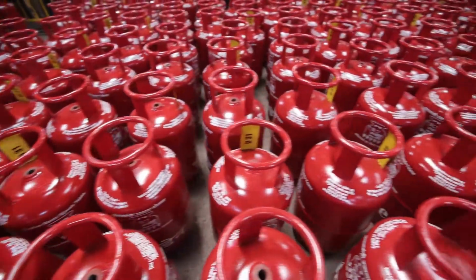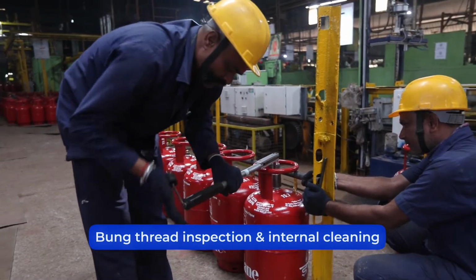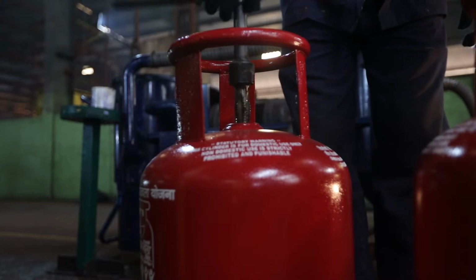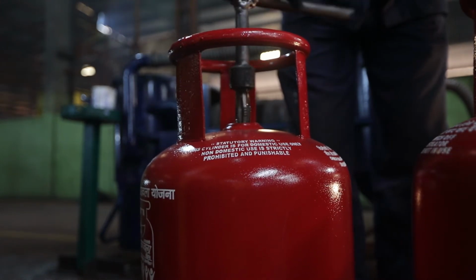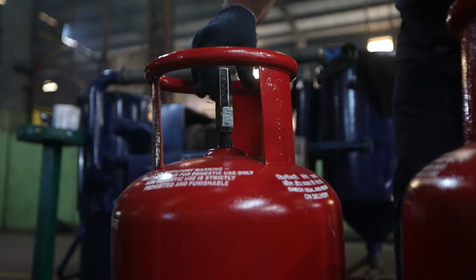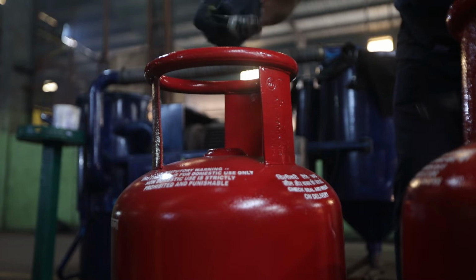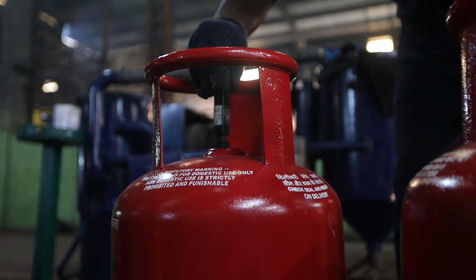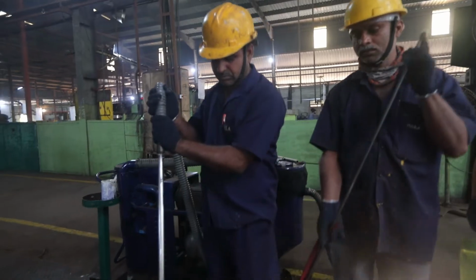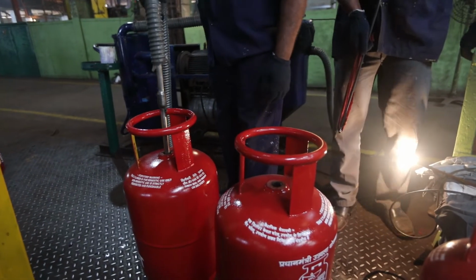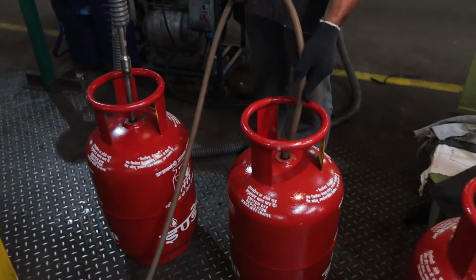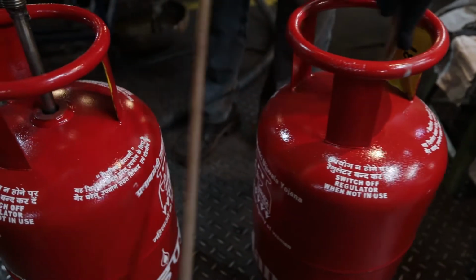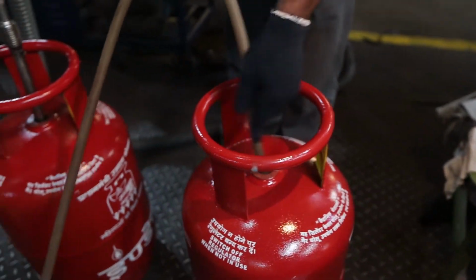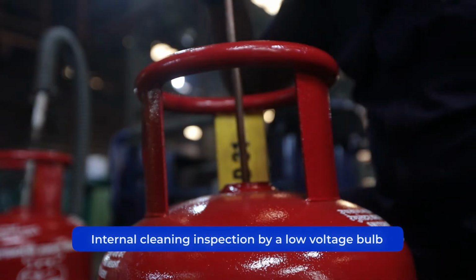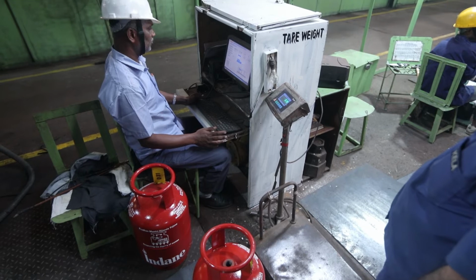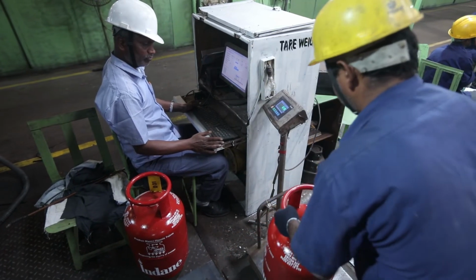An operation for bung thread inspection and internal cleaning includes: Step 1. Bung thread cleaning by a 3/4 inch NGT finishing tap and checking by L1 and L9 thread gauges. Step 2. Cloth cleaning to remove water traces. Step 3. Vacuum cleaning to remove scales, water traces and foreign particles from the cylinder. Step 4. Hot air drying by hot air blower. The cylinder's internal cleaning inspection is carried out with a low voltage bulb fixed on an extended rod. Visual checking is performed after inspecting the cylinder.